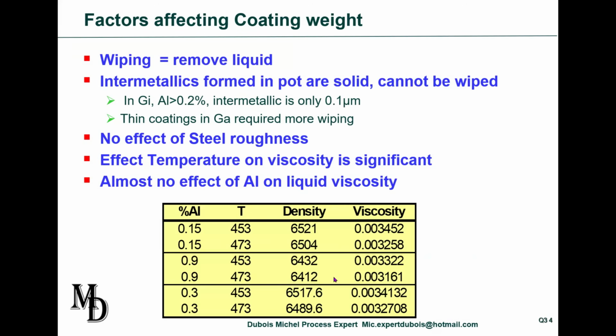Yes, I can. The factors that affect coating weight are related to removing a liquid. Wiping is nothing else than removing a liquid. Of course, you have to keep in mind that if the strip makes some intermetallic, and especially thick intermetallic in the pot, it cannot be wiped. This is why galvannealing is more difficult to wipe than galvanized. In GI, where aluminium is typically over 0.2%, the intermetallic is very thin. It's about 0.1 micron, not higher than that. So it means it has no impact. So there is no effect on steel roughness, at least on coil sheet. This has been proven by different research people.